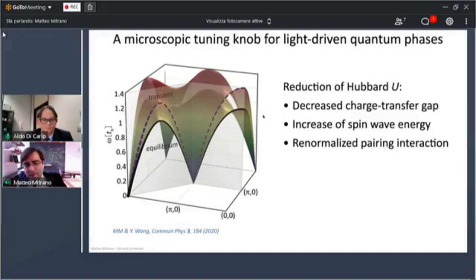Based on the results of our experiments, if you can find materials in which you can dynamically enhance the spin fluctuation spectrum, that's also another possible prescription. If you can increase the characteristic energy of the spin fluctuations, that could also be a beneficial effect.